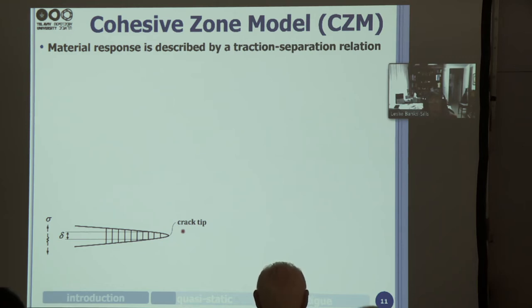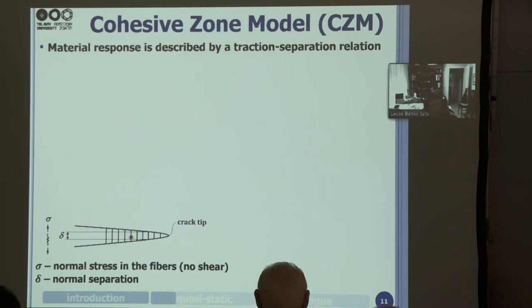So what we're going to do, we carried out the test. We now want to create a cohesive zone model based on these tests. And what we need is a traction separation law. And we assume that there's no shear. There's some shear, but it's minimal, we believe. And so we have sigma, which is the normal stress in the fibers, which are holding together the crack or the delamination, and delta is the normal separation.